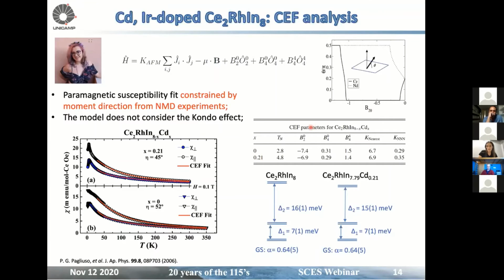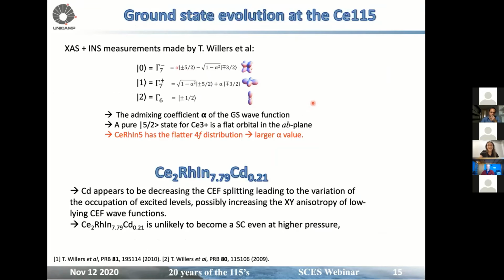That's the crystal field parameters, and that's the scheme. And what we could see here is that the cadmium is lowering the levels to lower energies. And I don't need to explain again the beautiful results from Professor Sabrin's group showing the alpha behavior of the crystal fields of the ground state wave function as a function of rhodium and iridium. So we just use that to have an idea and conclude that cadmium appears to be decreasing the crystal field splitting, leading to a variation of occupation of excited levels, so possibly increasing the XY anisotropy.